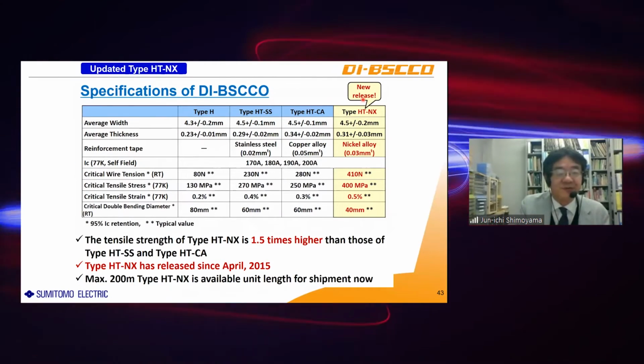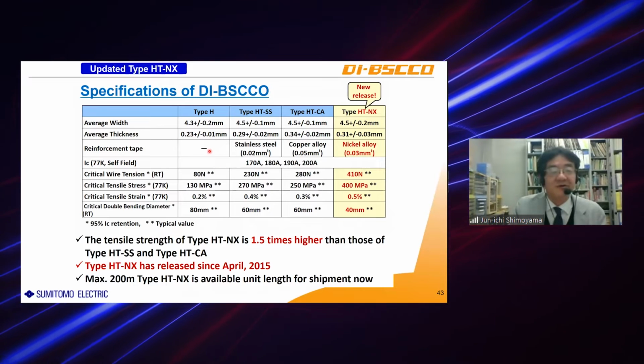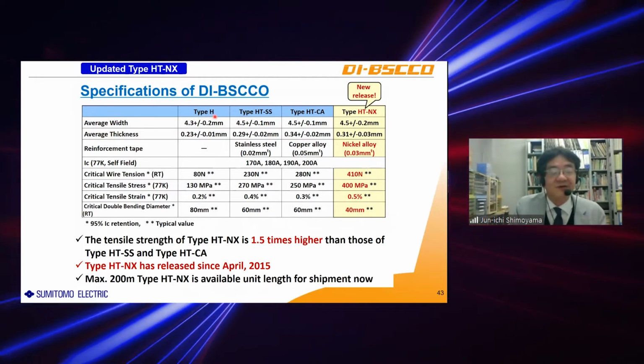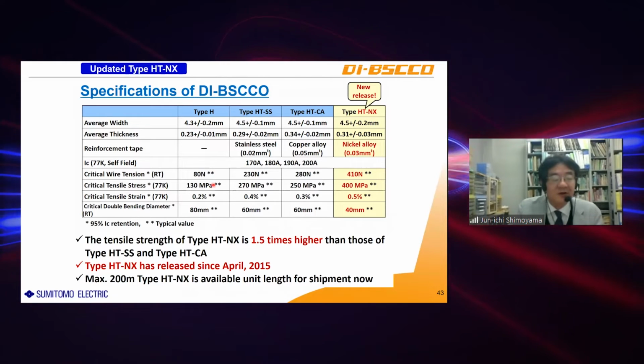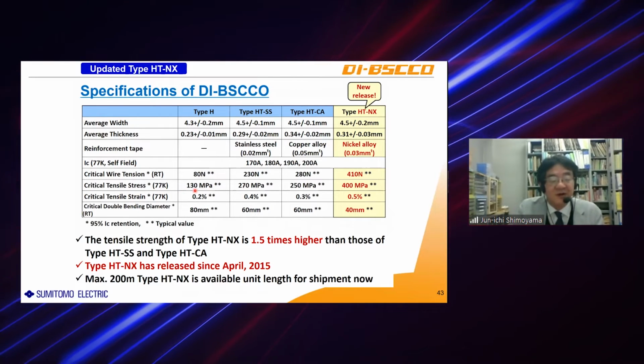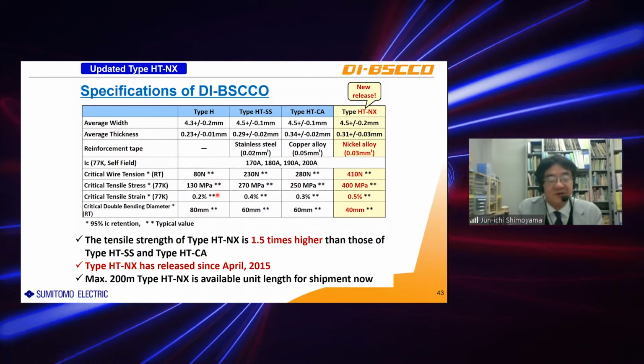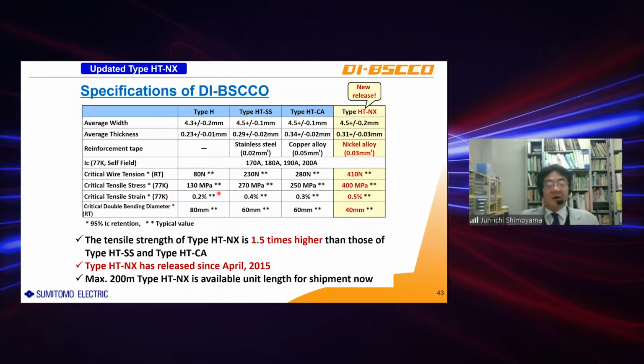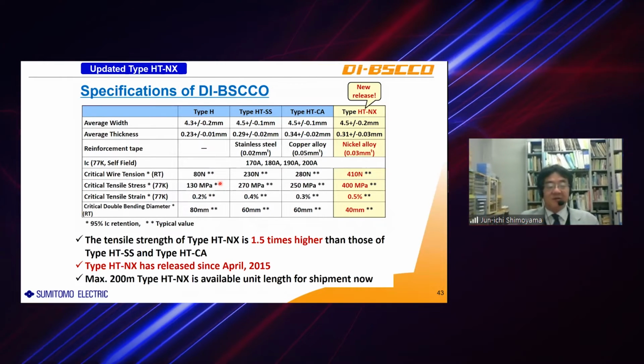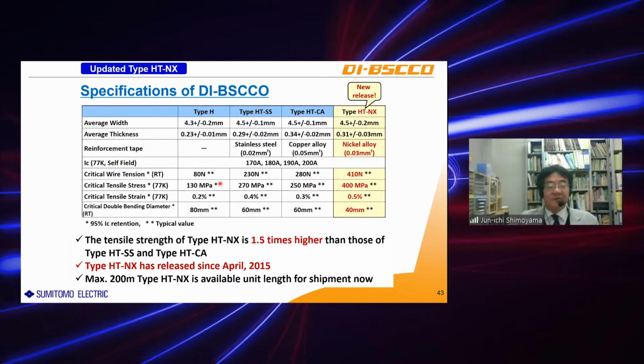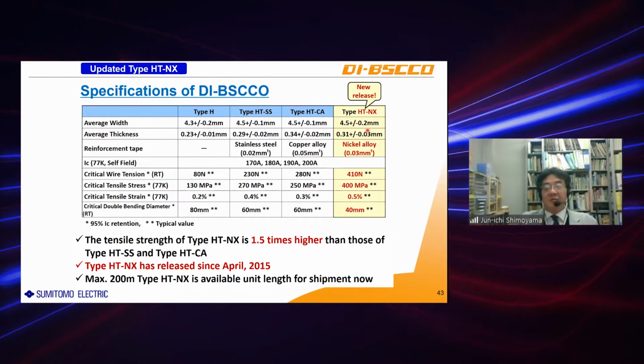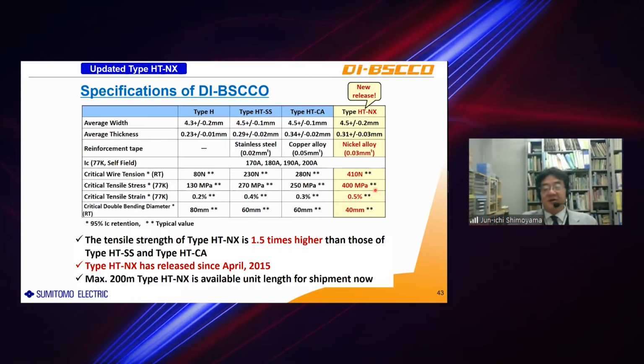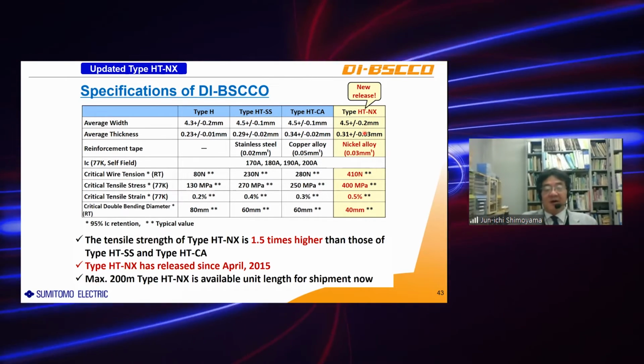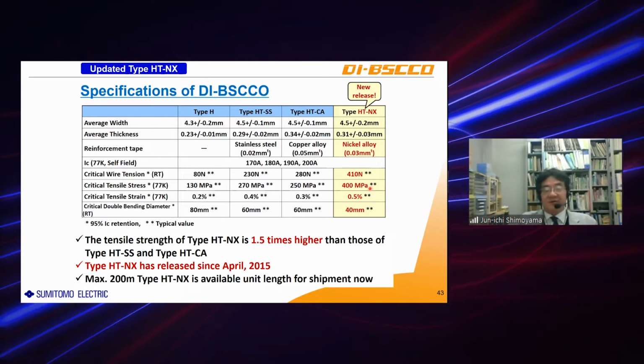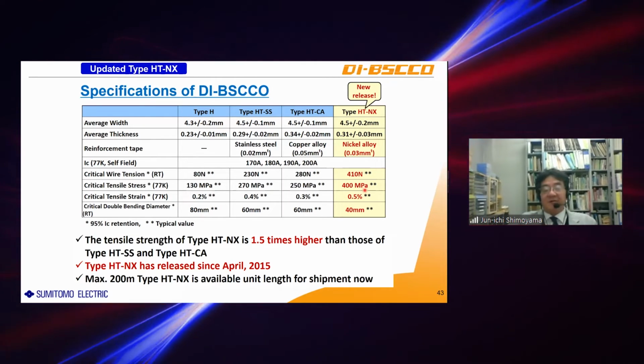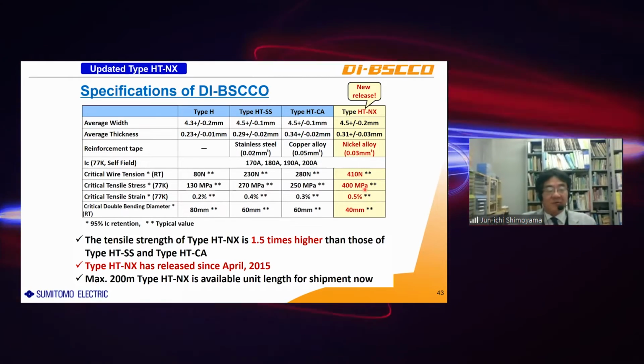So this is the specification of the DI-BSCCO tapes. The bare superconducting tape, we say type H. Bare means a silver sheath tape without reinforcement, and has very low critical tensile stress, 130 megapascal. This cannot be used for a superconducting magnet generating very high field, because electromagnetic force is much larger than this value. So we will use this type HT-NX tapes in our program. These tapes are reinforced by nickel alloy, and the critical tensile stress is around 400 megapascal. This is high enough to be used in our program.